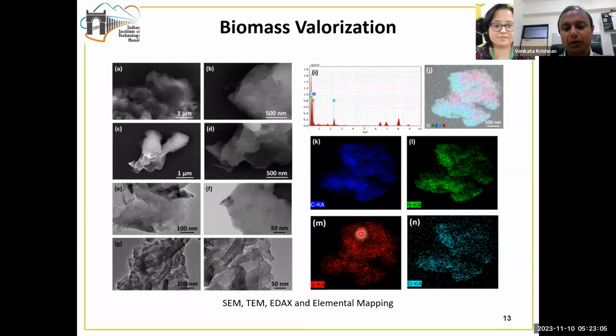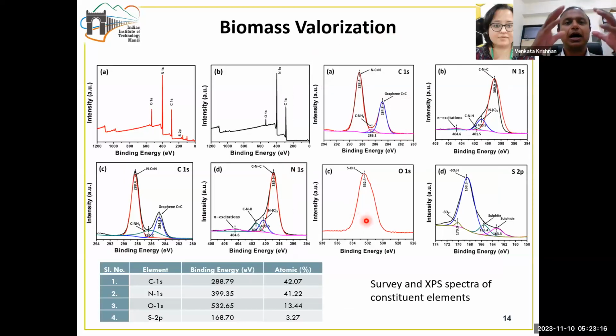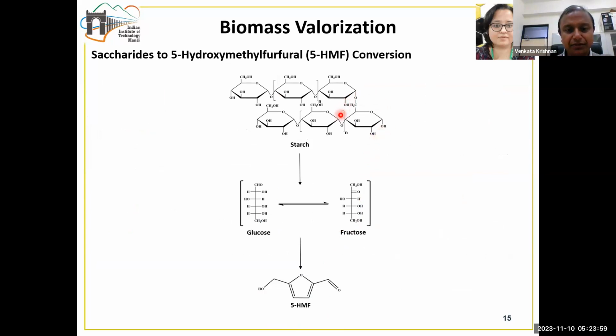We also did the elemental mapping to figure out the locations of each of the elements present in the sample. And we also did the EDAX analysis to understand the presence of the different constituent elements. Then we did a detailed XPS spectroscopic analysis in order to understand the electronic interactions happening between the different elements involved in the sample: how the nitrogen interacts with the carbon, and how the carbon interacts with the sulfur and subsequently the oxygen. And since this is a surface sensitive technique, we are also able to figure out the atomic percentage composition of the different elements on the surface. Especially since sulfur is one of the heteroatoms here and it forms the catalytic active site, we were able to even decipher the amount of sulfur present on the surface, which was found to be about 3.27 atomic percent.